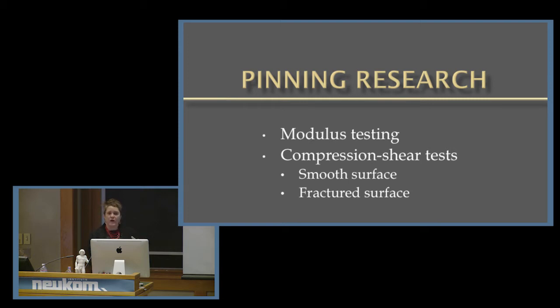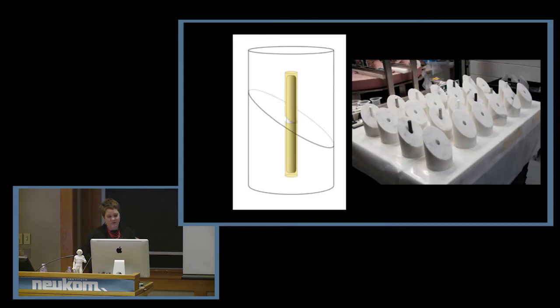We were trying to mock up these critical joints in the sculpture, like the knee, where there's a really sharp angle, and the ankles, where there's also a sharp angle. So we had this mock-up approach to the test samples. Here is what some of them looked like as they were being fabricated, and then a diagram showing what it looks like inside. There's a pin inside that's held in with epoxy. And we tested a lot of different materials, carbon fiber, stainless steel, fiberglass, polycarbonate, a range of moduli, which is the stiffness of the material.